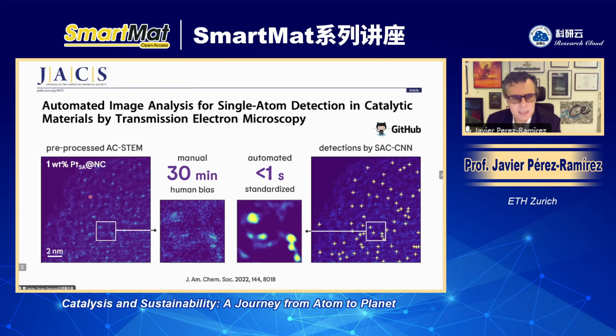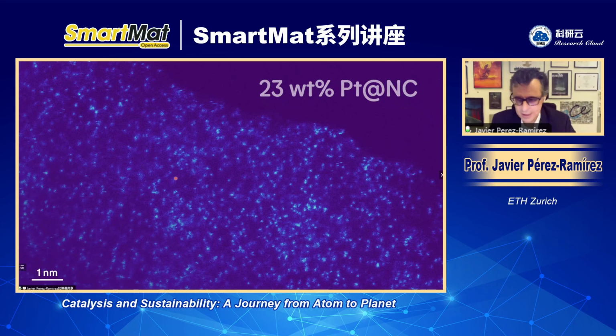And what you can see here is the same image as you see on the left with annotations of single atoms according to the neural network. This is a convolutional neural network which detects single atoms on the basis of probability maps. So what you can see is the probability map of the single atom. You can see here the bright spots indicating single atoms, and the algorithm, what we call SAC-CNN, which is freely available in GitHub. You just need to upload your microscopy image and you will get the analysis done in less than 1 second per image, compared to 30 minutes if you do it manually. It gives you, after huge training that we did for the algorithm, the detection of these single atoms. So this is a tool that also contributes to further standardization.